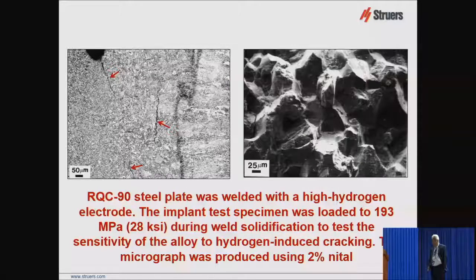Here's a RQC90 steel plate that was welded with a high hydrogen electrode deliberately to see what would happen. This is an implant test specimen, which is a mechanical test to see the effect of the welding process on the surface. The implant test specimen was loaded to 193 megapascals, which is 28 KSI, during the weld solidification to test the sensitivity of the alloy to hydrogen-induced cracking. And you can see there's a crack here.